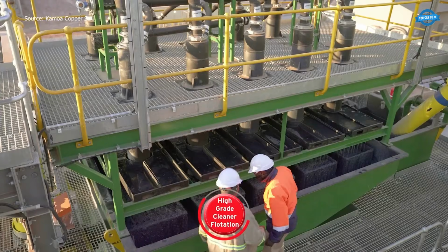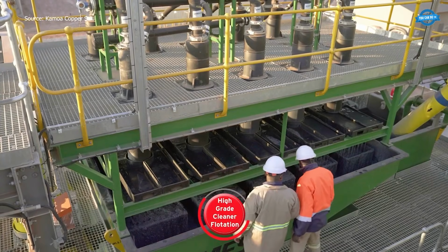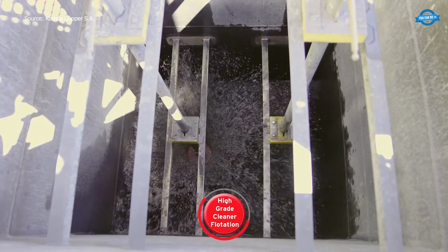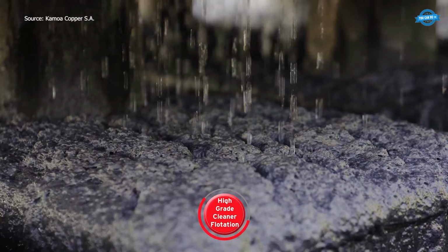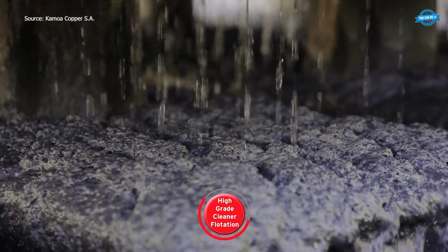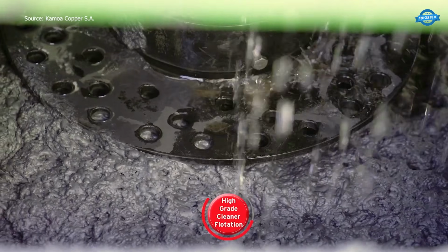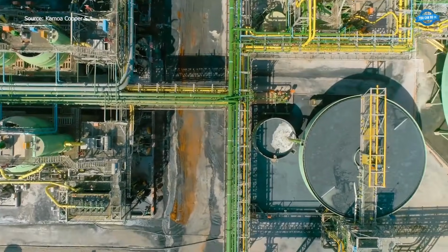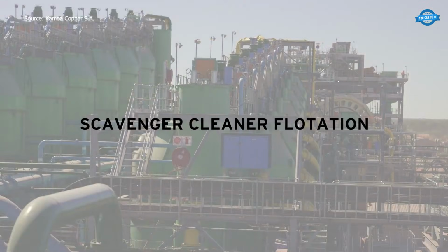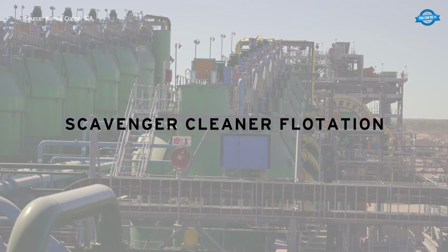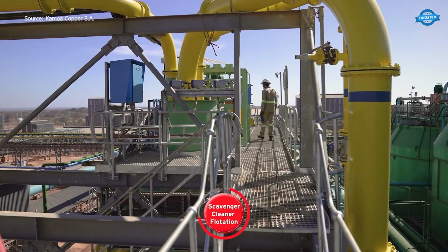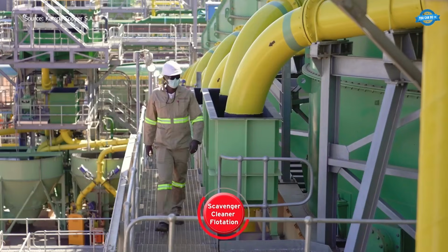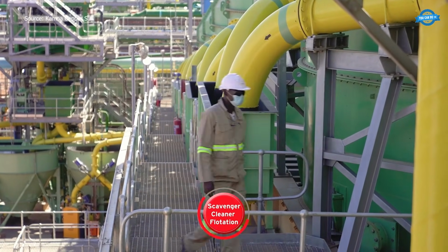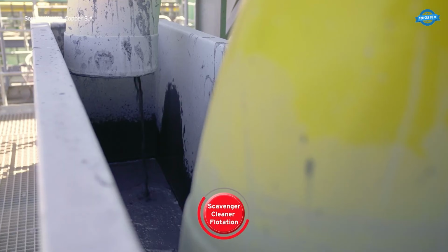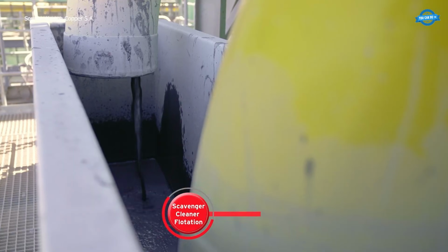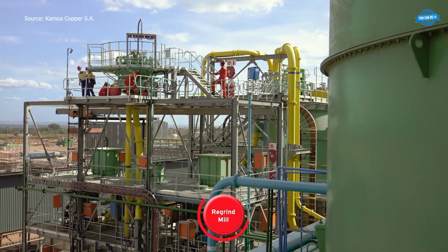Run-of-mine ore is delivered at 475 tons per hour to the crushing and screening plant, preparing the material for high-pressure grinding rolls. The grinding produces finely liberated copper sulfide, ready for the flotation process. In the rougher scavenger flotation circuit, reagents are introduced to form a slurry, then air is blown into the flotation cells, lifting copper minerals to the surface. The material passes through high-grade cleaner flotation and scavenger cleaner circuits to maximize copper recovery.